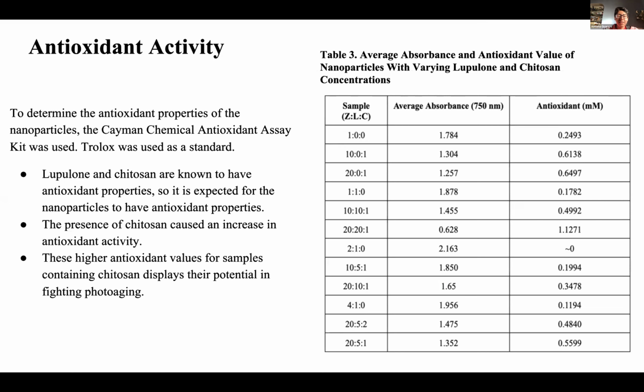Here we have antioxidant activity. We measured this by using the Cayman Chemical Antioxidant Assay kit, where Trolox was the standard. You should notice here on the side that since lupulone and chitosan were both known antioxidants, we expected our nanoparticles to have these properties. And you'll notice that the particles with chitosan had a slightly better antioxidant property, which is what we were hoping to see. We were hoping to see a synergistic effect between the two of them since they were both known to have these properties. And this is good for displaying their potential in fighting photoaging.